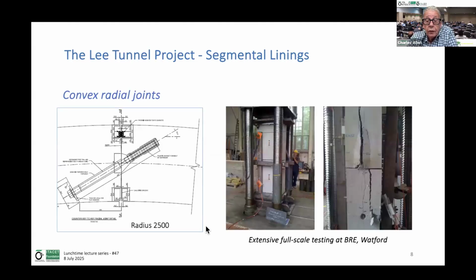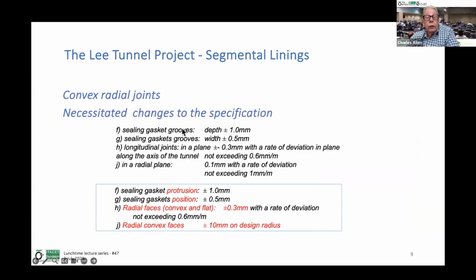The radial joints, we cast some full-size units of concrete with curved radial joints with a radius of 2.5 meters on the joint, and we did extensive full-scale testing at the Building Research Establishment at Watford, and we decided to adopt the curved joints, which actually meant us changing the specification because the original specification had gasket grooves, and we were using cast-in gaskets, and the radial plane on the radial joints. So we changed the gasket from grooves to protrusions, and the radial convex faces plus or minus 10 millimeters on design radius.